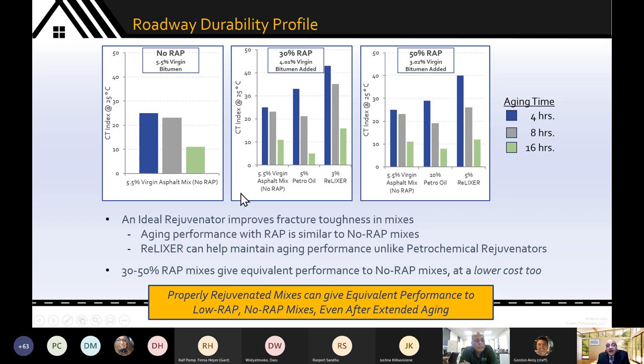We took this data and we just put it here and compared it to two cases, both 30% wrap, both about 4% virgin bitumen. Case A, rejuvenated with a petro oil, 5%. Case B, with a bio oil, 3%. What you can see is day one properties, the 4-hour aging properties of both are fairly similar to the material with no wrap whatsoever. It's only when you begin to age it do you start seeing changes. And the petro oil rejuvenated sample does not quite show the same long-term aging properties as does the mix made with no wrap. This is true of both the 30% wrap case and the 50% wrap case.